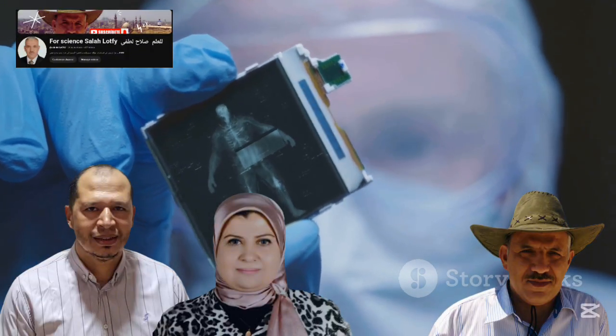H4, 172-fold; H5, 194-fold; H6, an impressive 244-fold of its dry weight. This extraordinary capacity highlights the role of both fillers. CaCl2 boosts hydrophilicity, while charcoal introduces porosity, creating a superabsorbent composite ideal for humidity sensing.